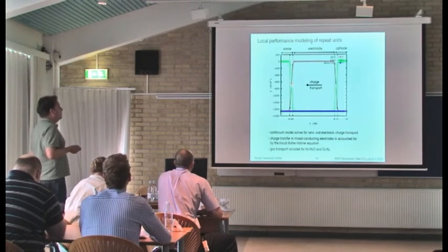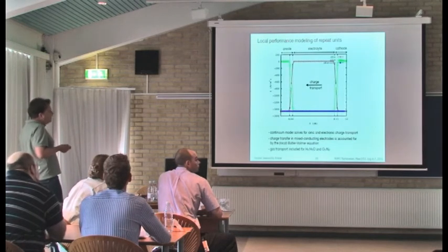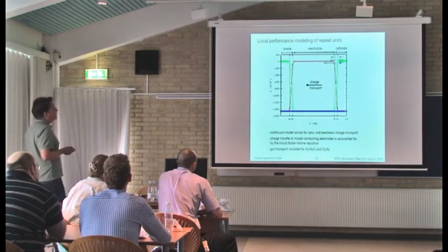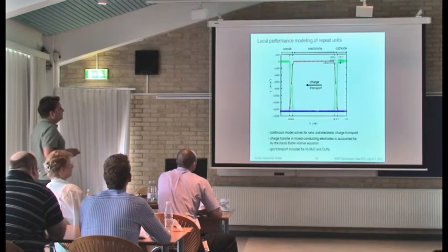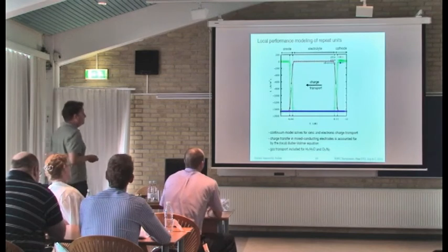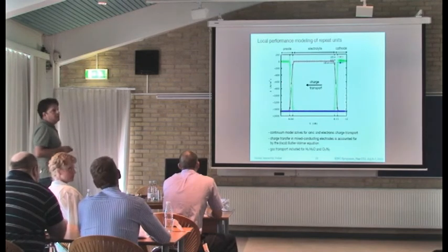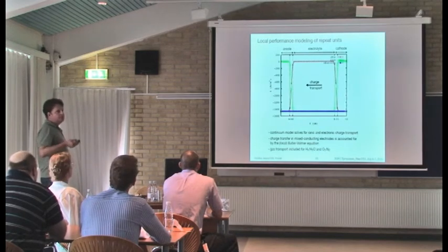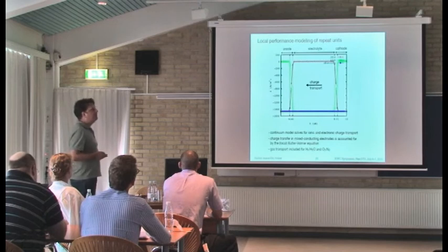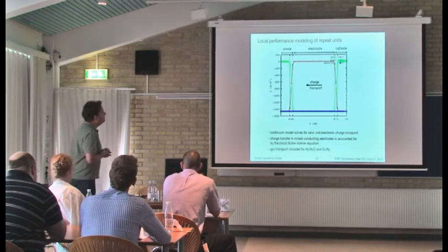So you see how the electrical current increases within your mixed conducting electrodes, and similarly, due to the conservation of charge, the ionic current drops to 0, and the ionic current stays constant within the electrolyte. We use the Butler-Volmer equation to model the charge transfer, and yes, this is certainly not perfect. It needs more investigation, but for now we really wanted to focus on microstructure and keep everything rather simple.